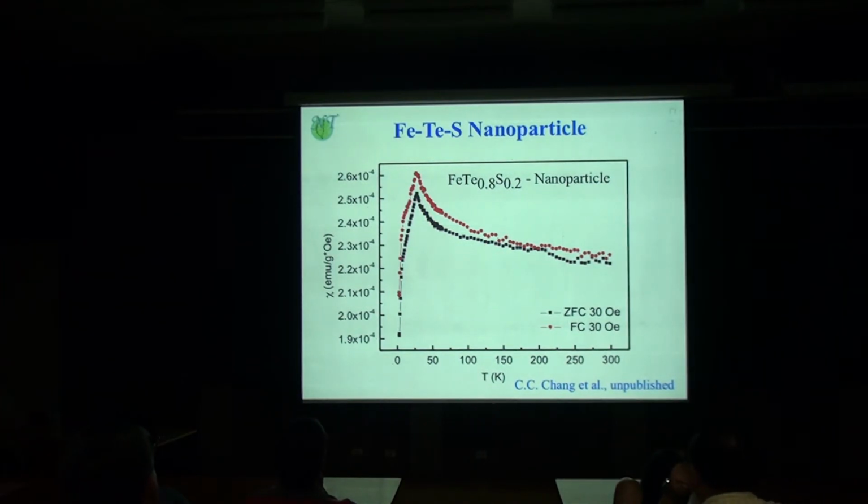Okay, so that's a good indication that by using nanoparticles we can stabilize a superconducting phase with a higher temperature without any external pressure. And of course, the surface or interface of the nanostructure already has existing stress, so that gives you this feature.